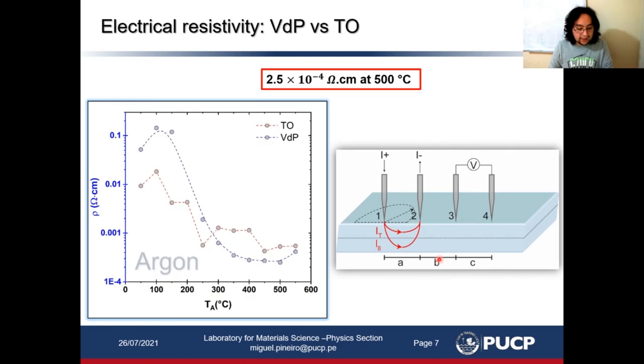As the electrical current has lateral behavior, we take the two layers as two parallel resistors. In this way, we calculate the electrical resistivity from transmittance measurements and compare with the electrical resistivity measured by Van der Pauw technique, as shown in this figure. We can see both resistivities present the same behavior. The lowest electrical resistivity value was obtained at 500 degrees Celsius.